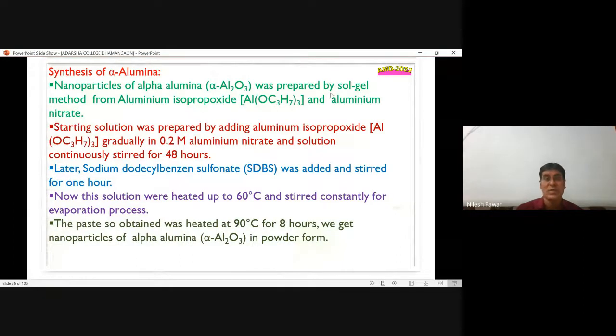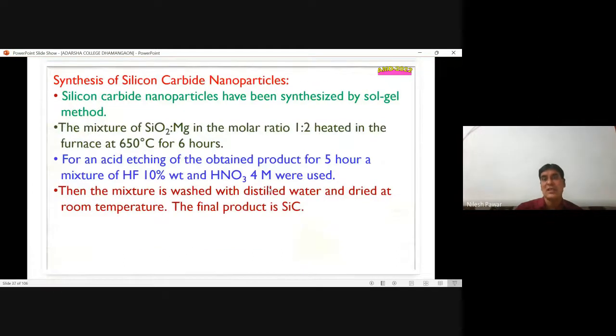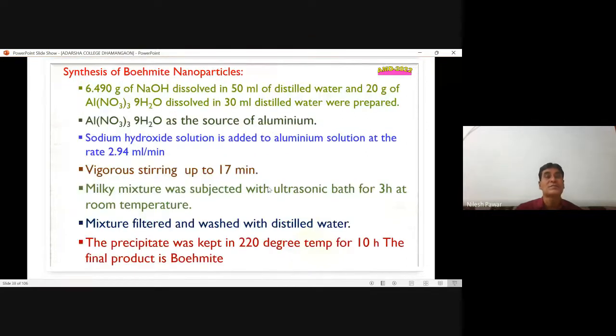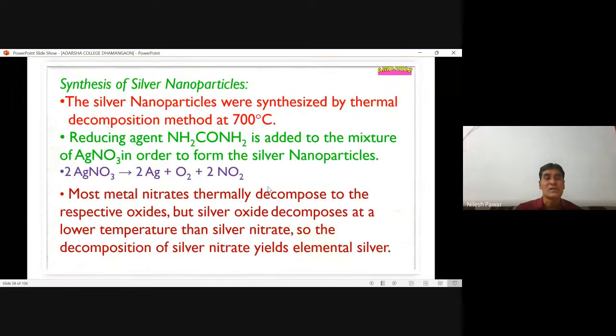Nanoparticle of alpha alumina was prepared by sol-gel method from aluminum isopropoxide and aluminum nitrate, and this solution can be converted into the gel, and after then we dried that, and by calcination that can be converted into the nanoparticle. This is a synthesis of silicon carbide nanoparticle because this nanoparticle plays a very important role, especially in power generation. Boehmite nanoparticle plays a very important role in the agriculture field. We have synthesized this nanoparticle by using various techniques also. Silver nanoparticle, this is a metal nanoparticle. We have synthesized by using again sol-gel techniques and by eco-friendly, by using a plant extract also.